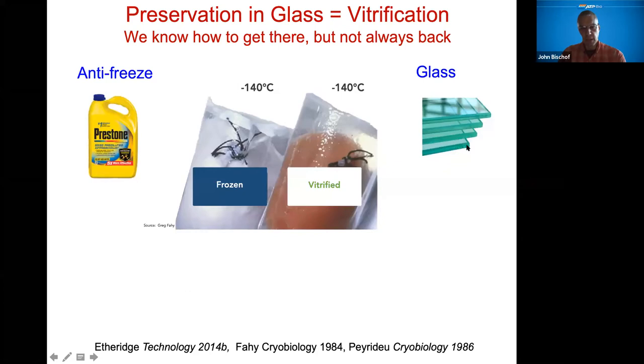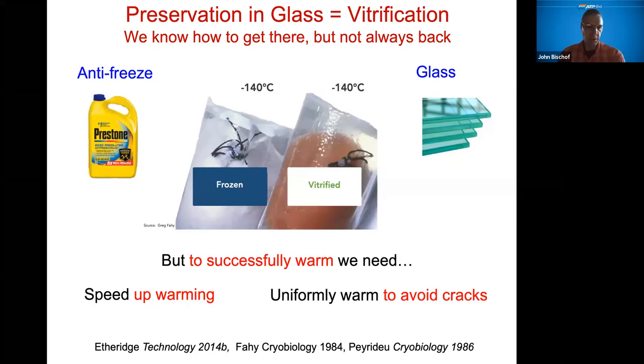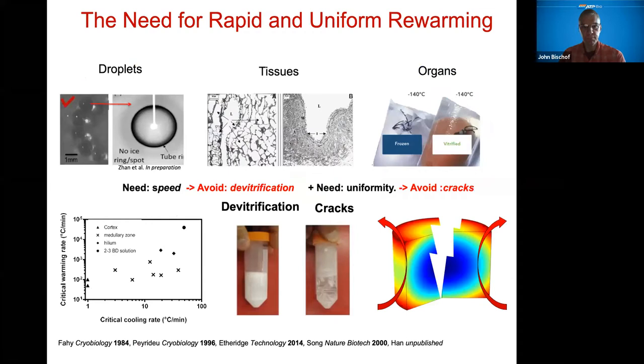But the problem is coming back. And so to come back, you need to come back fast enough so that you don't freeze or devitrify, you know, go from a glass to a crystalline phase on the way back up. And you need to do this in a way where it doesn't crack. So everyone knows glass is brittle, just like that ice cube. If you drop it into that water, if you have too much of a gradient in the system, it'll crack. So these are the two big concepts that we try to deal with in my group when we're dealing with these vitrified systems. So in all cases, what we really need is rapid and uniform rewarming to address this.